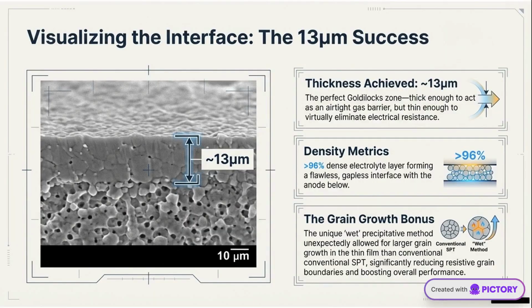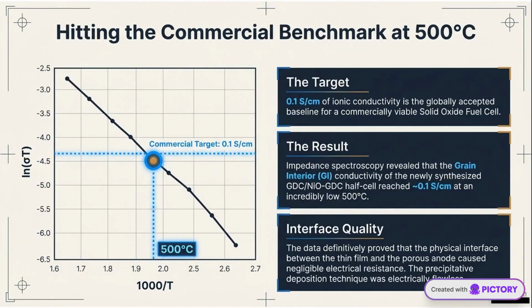With a thickness of approximately 13 micrometers, the electrolyte layer acts as an effective barrier while virtually eliminating electrical resistance. This balance is key to enhancing SOFC performance. Our GDC/NiO-GDC half-cell achieves the commercial benchmark of 0.1 S per centimeter at 500 degrees Celsius. This success underscores the effectiveness of our interface quality and deposition techniques.